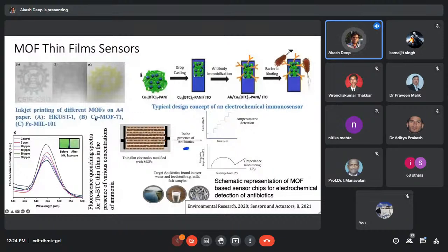Then this is a typical design concept of an electrochemical immunosensor. How we develop the electrochemical immunosensor: we take our nanomaterial, we drop cast it onto the surface of the electrode, the working area of the electrode. Then we modify that material film with antibodies, and then it becomes applicable for the selective detection of bacteria. And here you can see that we can use amperometric detection methods or impedance spectroscopy based methods for analyzing the reactions that are taking place between the sensor and the analyte.